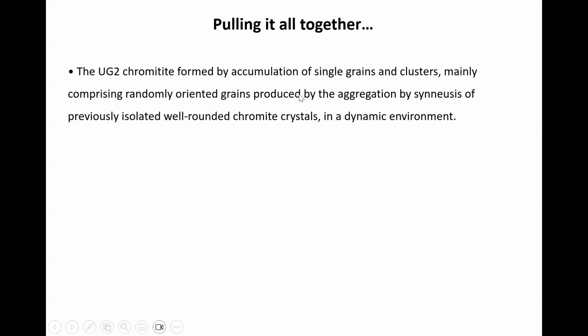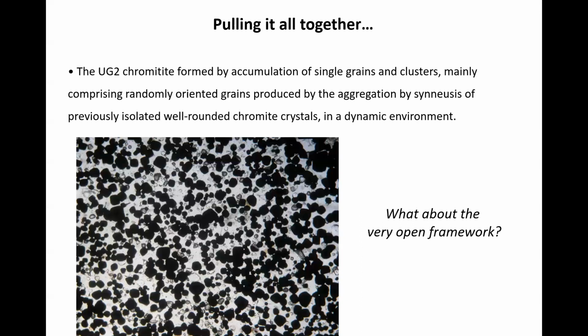I reckon that this chromitite, all the evidence that we've got, points to accumulation of single grains and clusters, mainly the clusters are rounded grains, so they're randomly oriented together, and they were aggregated by synneusis in a dynamic environment, as shown by that lineated orthopyroxenite.